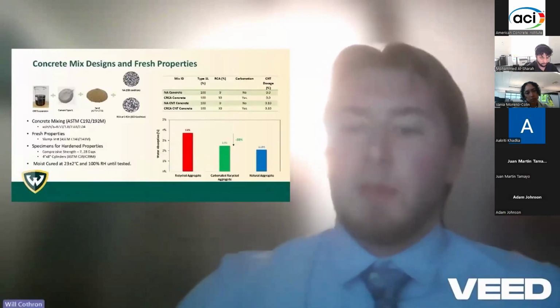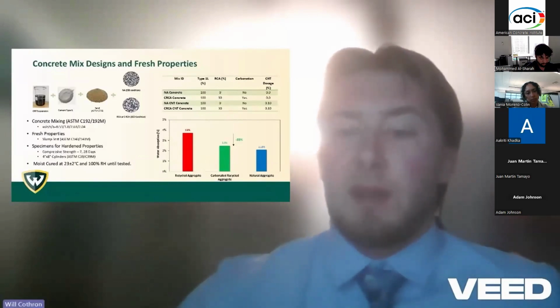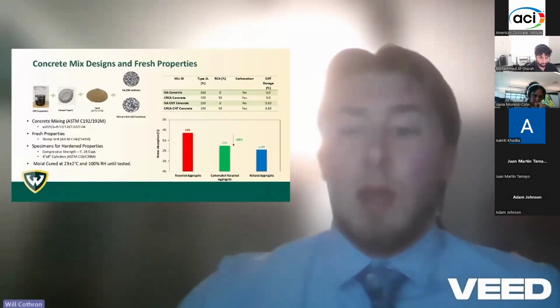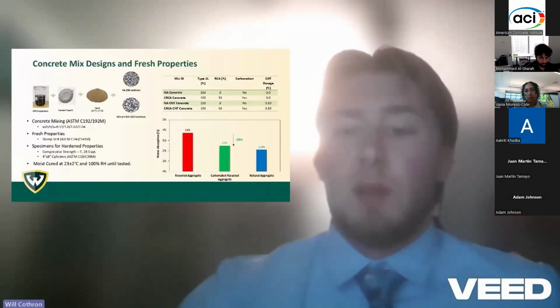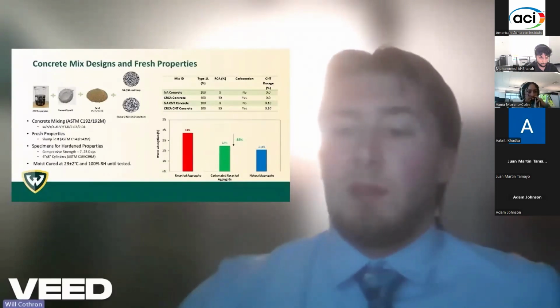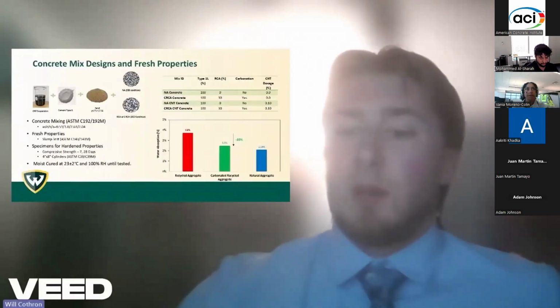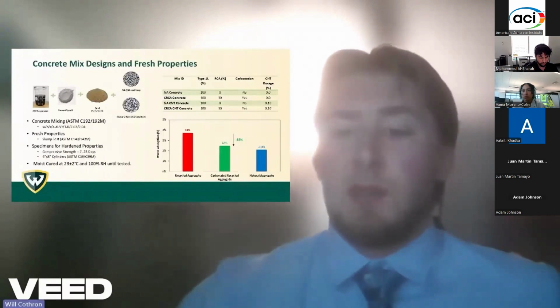In our study, we developed different concrete mixes to evaluate the effects of using recycled concrete aggregates, carbonation treatment, and carbon nanotubes on the properties of concrete. We prepared 4 different concrete mixes: our control, which is our standard concrete; our control CRCA mix, which is our carbonated RCA without CNTs; our CNT mix, which is our standard concrete with CNTs; and our CNT CRCA mix, which is our carbonated RCA with CNTs.